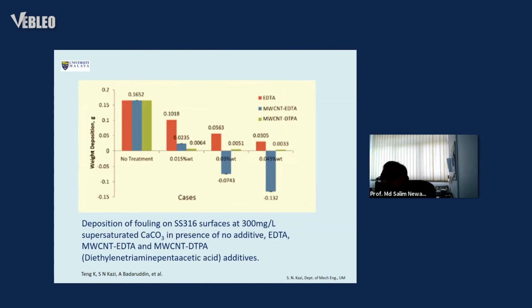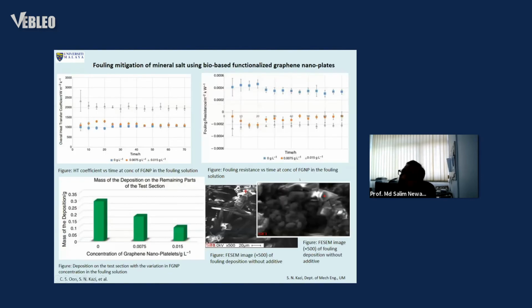The results are shown here: if it is DTPA, where the polymer is used, we get a very low level of deposition on the surface. In some other cases, we get higher. So once this is explored, it can be used for fouling mitigation and finally recommended. When we come to the mitigation of mineral salts using bio-based functionalized graphene nanoplatelets, it is also found that the heat transfer coefficient increases, as well as fouling mitigation is noticed there. From this result, it can be seen.